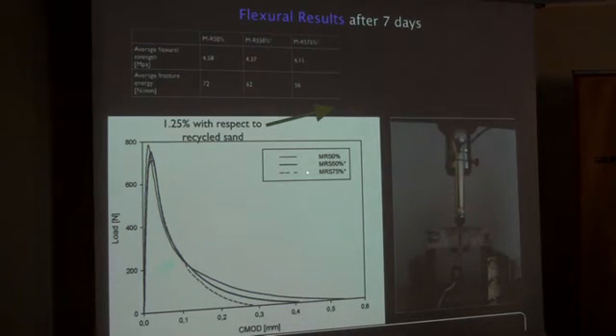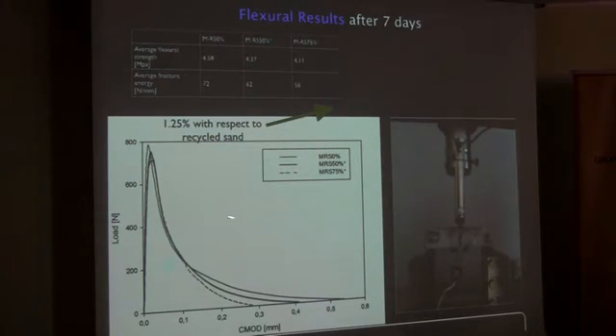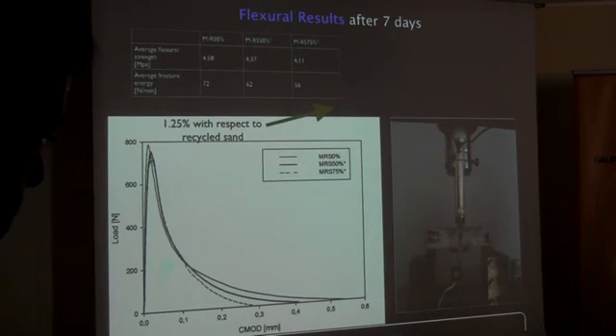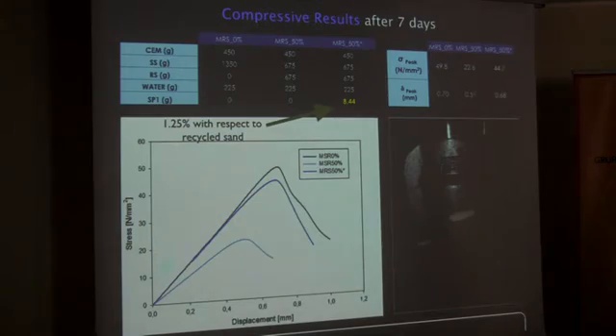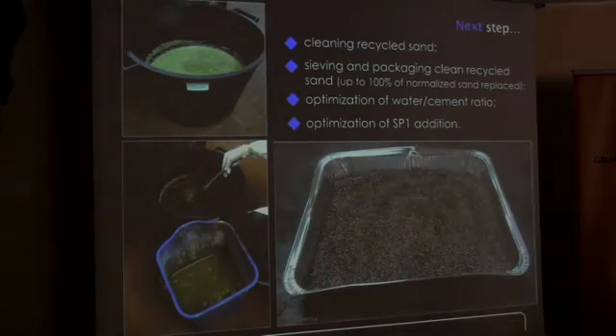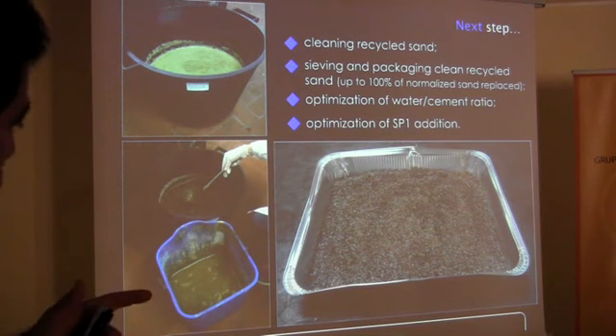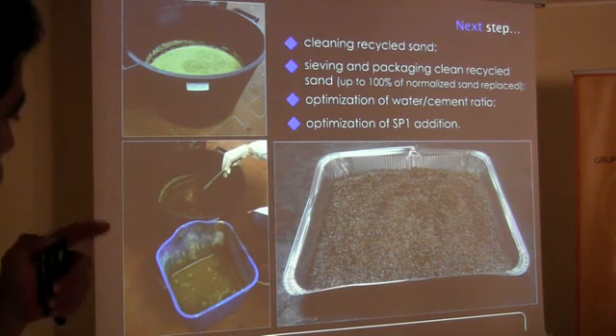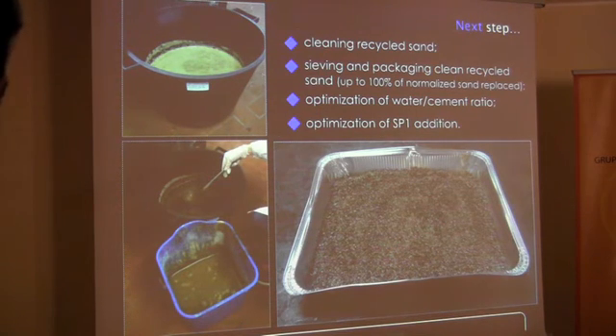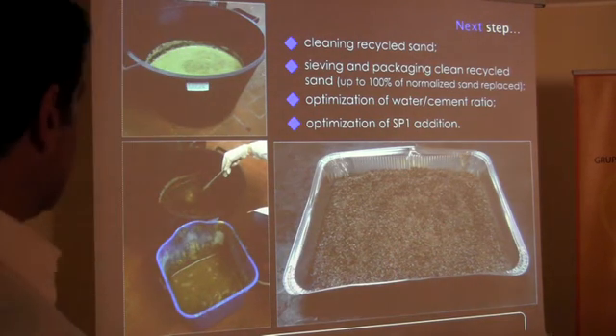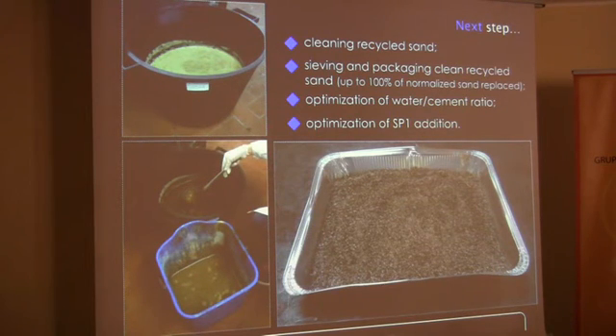We did the same in the second series, up to 75% of recycled sand, and of course adding superplasticizer with the same percentage, and we can observe that the variation is very, very close. So this pushes us to go on in this research. Of course, these are the results we obtained from compression. The second part will be to wash the sand before casting, because in the first series it was not washed. Of course, it's a very heavy process, but probably very interesting for the future.